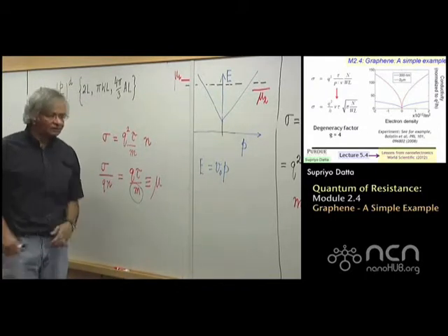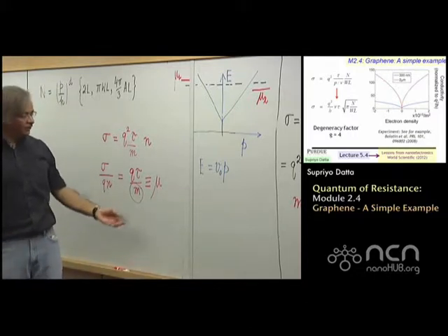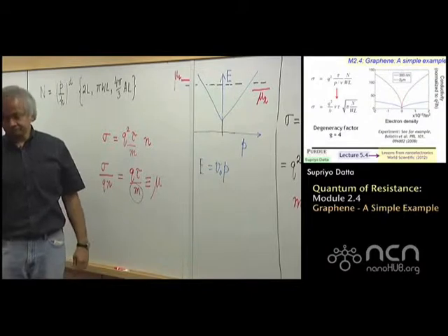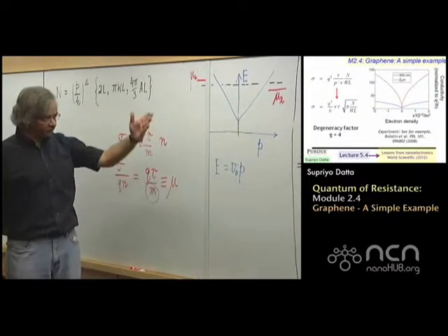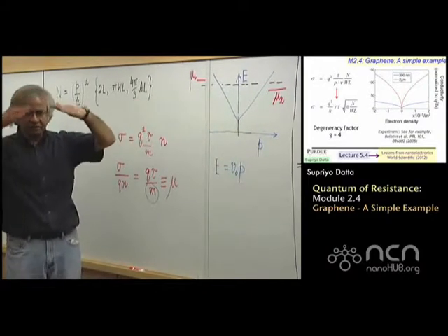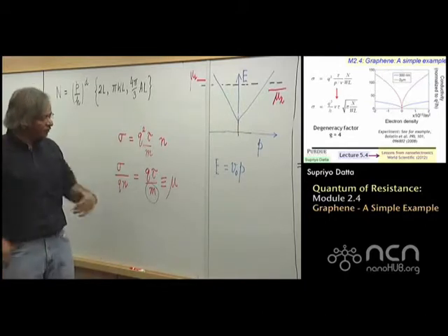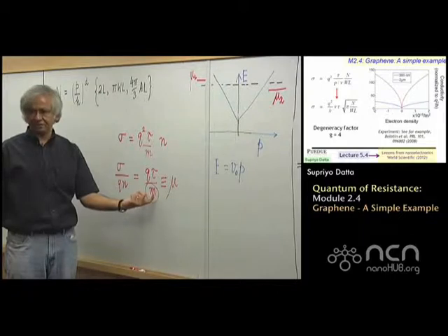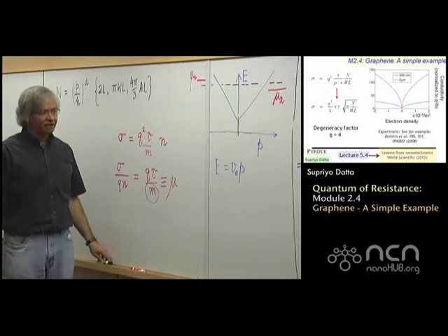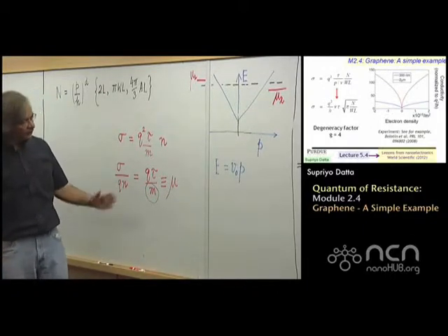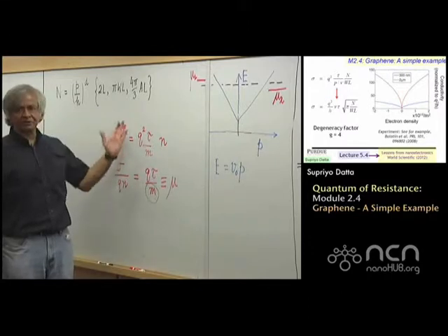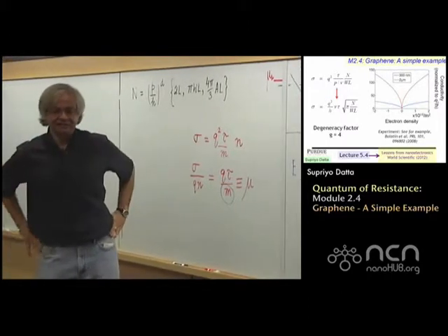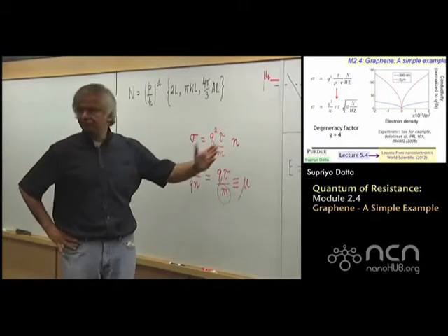All experiments show that when you measure mobility versus electron density for graphene, the mobility does go down in a way that you'd expect just from the fact that the mass is increasing. So this is an example where this simple picture we carry in our head needs to be qualified. Otherwise, a lot of well-established results can look pretty puzzling.